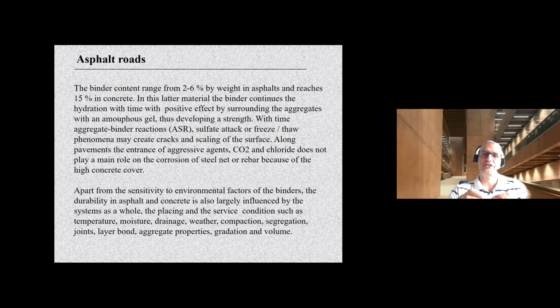In the cementitious material, the cement paste forms a gel that surrounds the stone aggregate and compacts them together with time. And the durability is actually only affected by some of the reactions that can occur along the interface between the cement and the stone aggregate. For instance, alkali silica reaction (ASR), sulfate attack, or freeze-thaw attack that may create cracks and then scaling of the concrete surfaces. While CO2 and chloride sometimes don't play a big role if the concrete cover over the steel rebars is high enough.